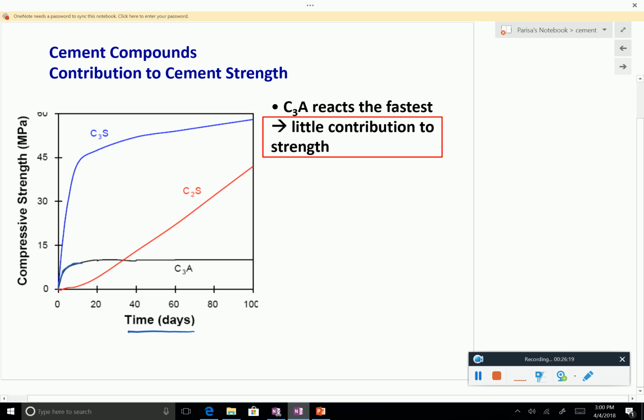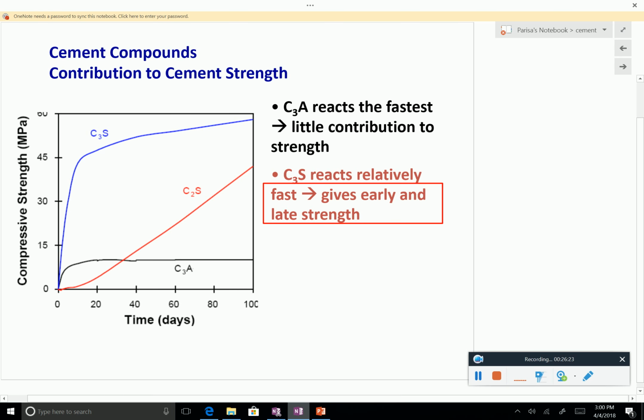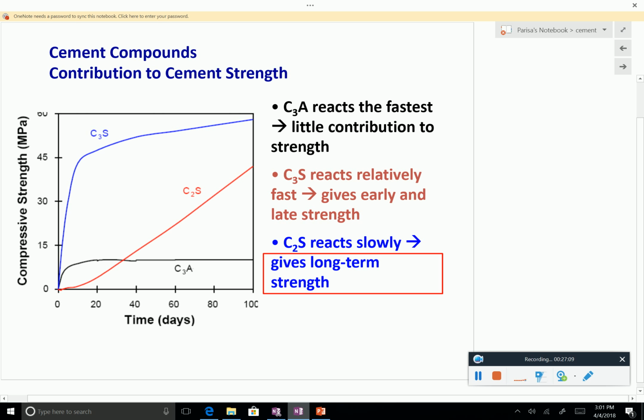This is C3A. Then we have C3S. This one is kind of similar a little bit. In the beginning, you have a large jump, so it helps developing early strengths. So for example, if you have a job where it is very important for you to be done quickly, it's a highway that has to be put in place, you have to open the lane very, very soon, then you want to use a cement which has this component a lot, because it gives you a lot of strength in the first few days. And afterwards, it doesn't reach a plateau as C3A. It still increases, but at a slower rate, as you can see. And then we have C2S, which doesn't really help in the beginning, but later on, it helps a lot. So that's helpful for the long-term strength.